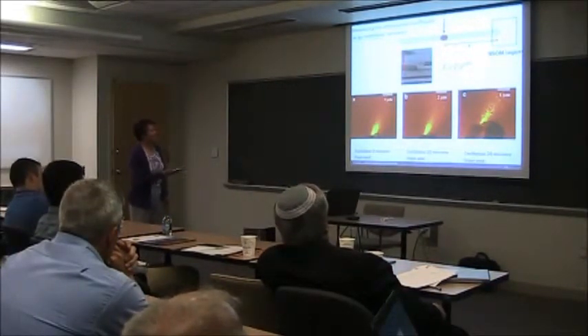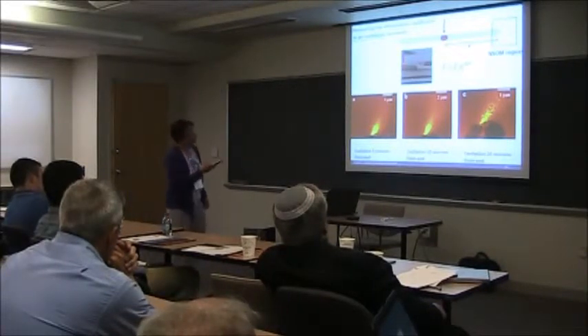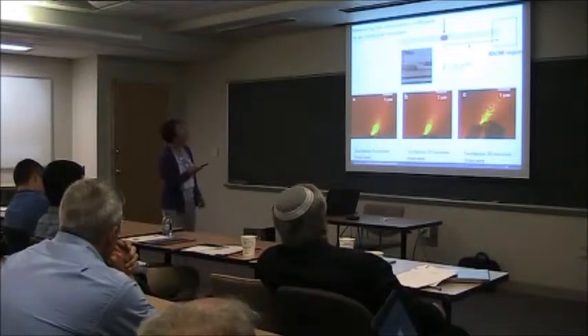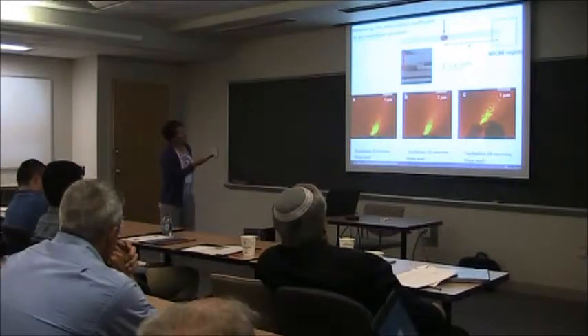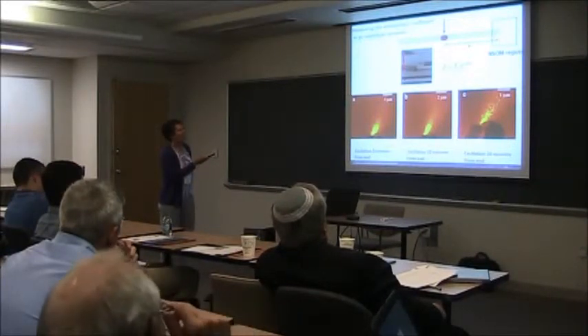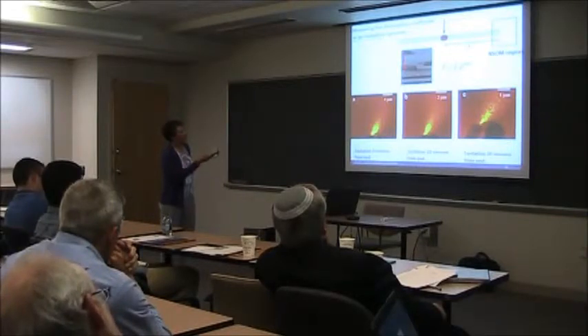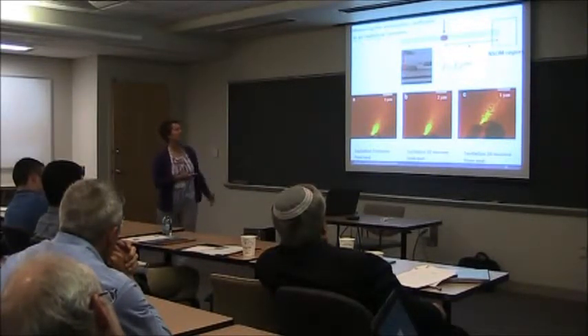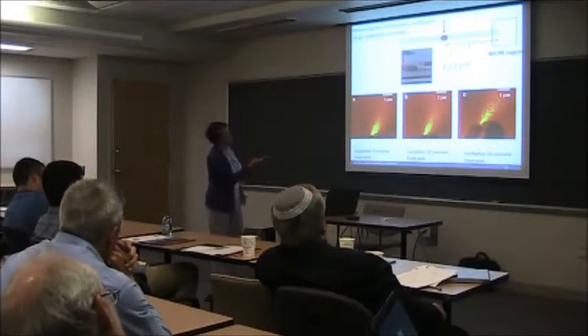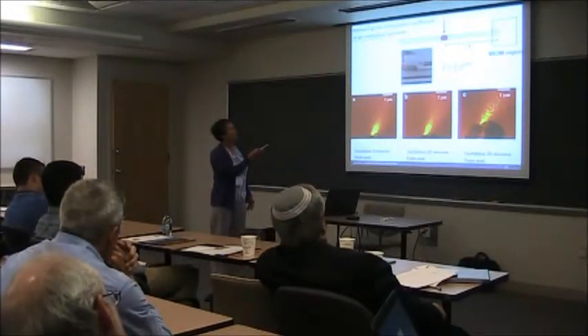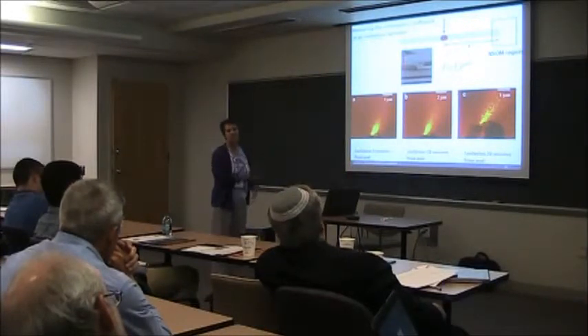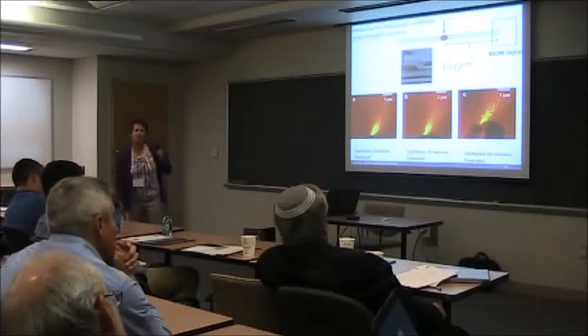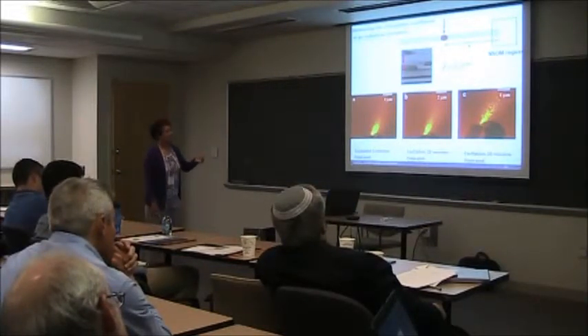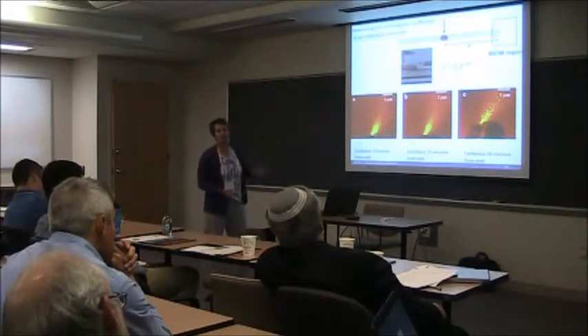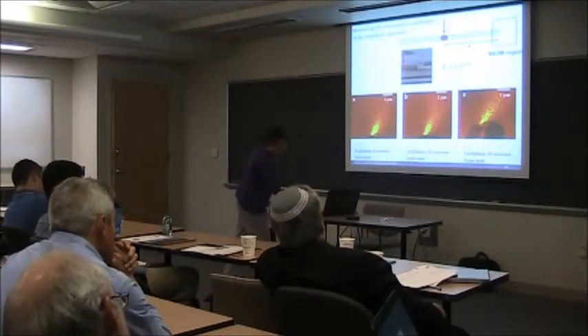Different photonic example. I showed you these pictures before. What we've done here is take these zinc oxide nanowires, I believe. So zinc oxide, and then, again, we have an SEM, so we can put the beam at any point that we want along the way, generate carriers, and then look at the intensity of the light that's emitted from the end of the wire. So what this allows us to do, actually, is a Beer's law experiment, where by varying the location of the excitation point, we can measure the absorption coefficient directly in an individual nanowire, which again could be done, I think, but it's challenging to couple light. And so here you can go in and generate the light wherever you want.